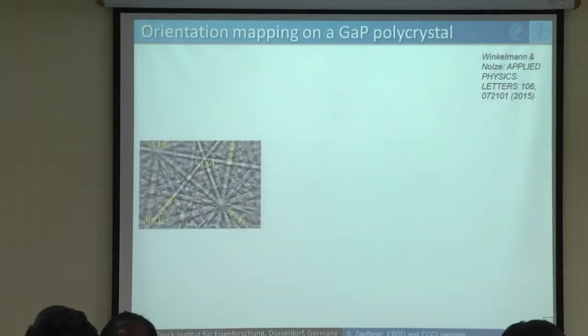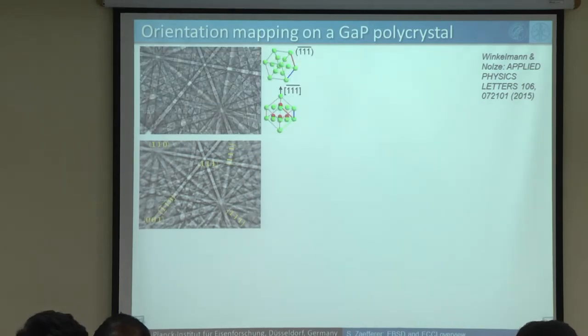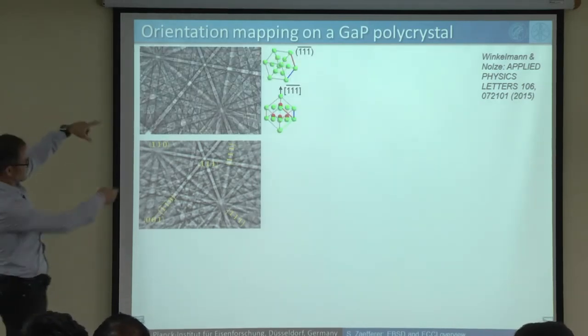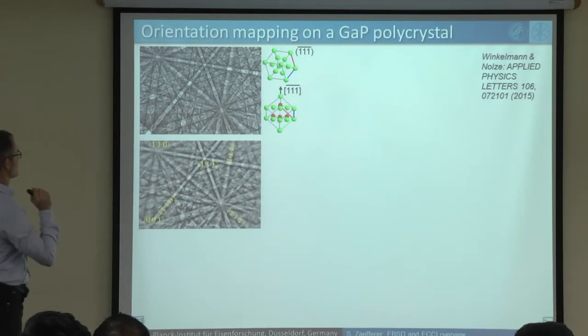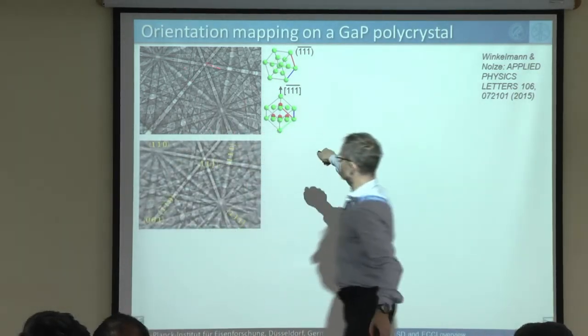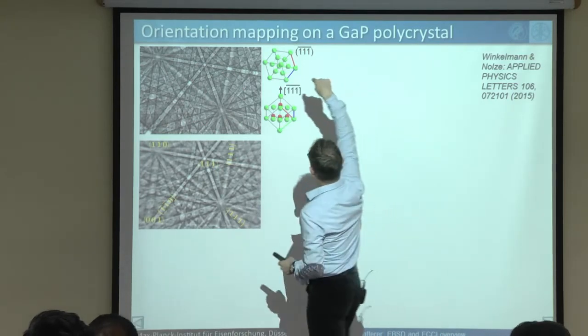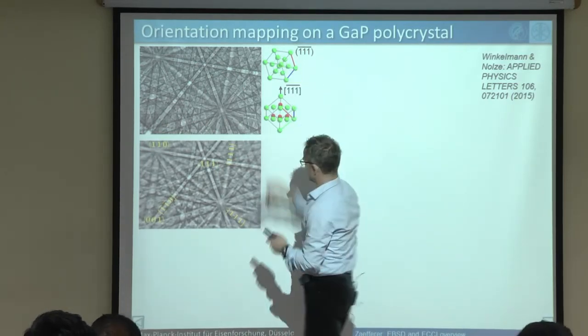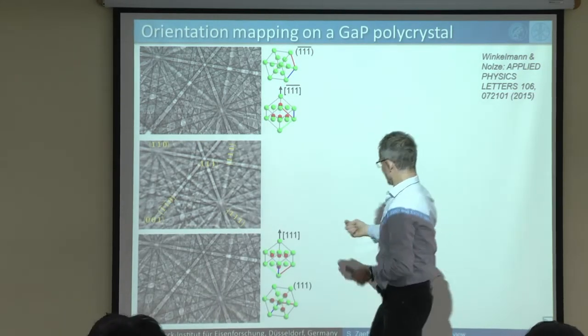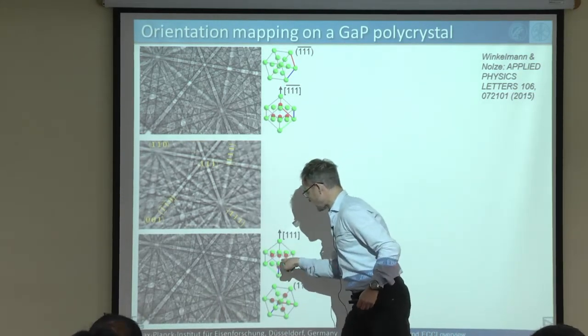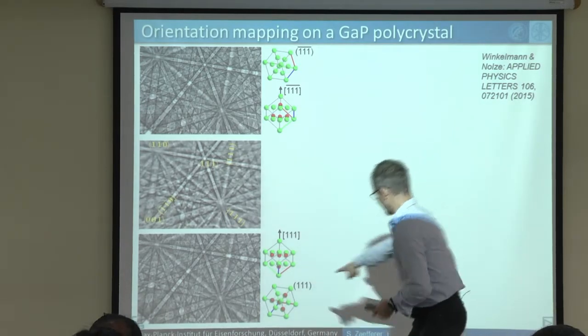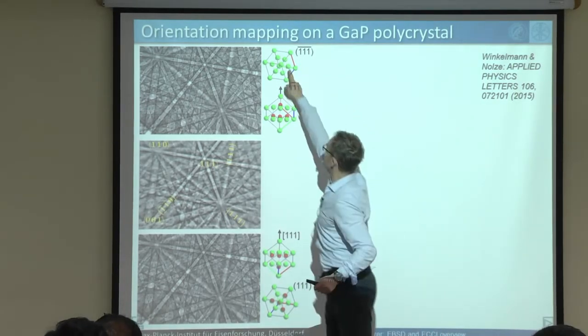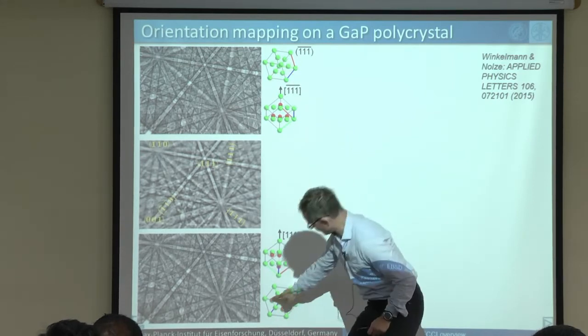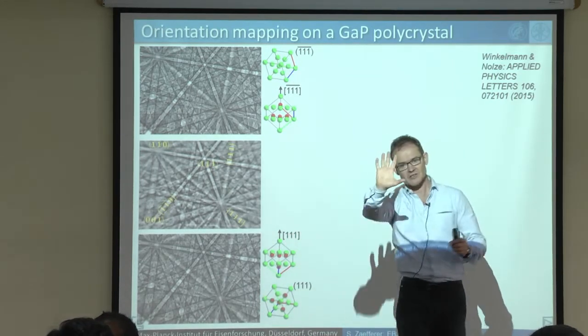This is a typical diffraction pattern obtained from this material. And now the question is, can EBSD separate whether we are looking in one direction or the other? This is a diffraction pattern simulated for the case that we are looking into the minus 1, minus 1, minus 1 direction. And this is a diffraction pattern for the case that we are looking into the plus 1, plus 1, plus 1 direction. Here we are seeing only the green atoms, and here we see also the red atoms. So we are looking in different directions of the crystal.